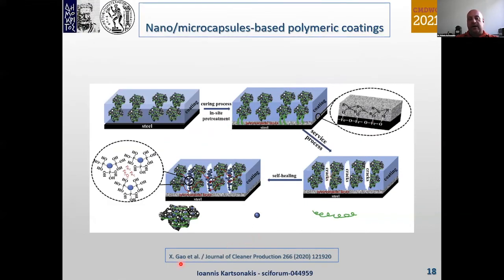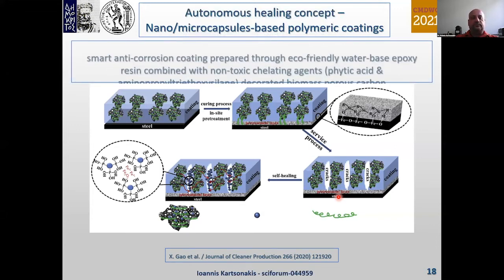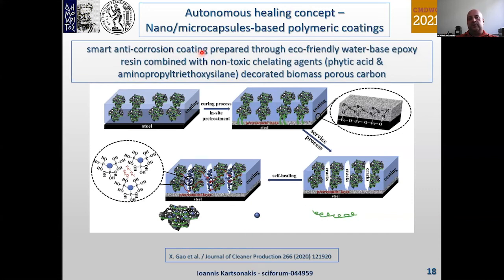In the work of Gao in 2020, microcapsules were also used: smart anti-corrosion coatings prepared through an eco-friendly water-based epoxy resin that was combined with non-toxic chelating agents. These healing agents were phytic acid and aminopropyl triethoxysilane, also phytic acid. And these two healing agents were grafted or adsorbed on biomass porous carbon.